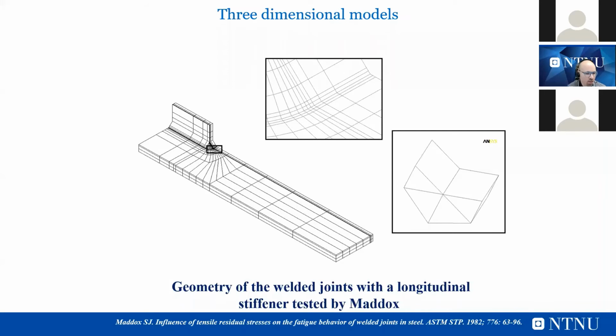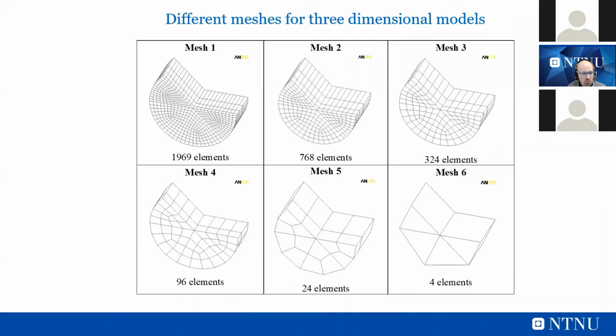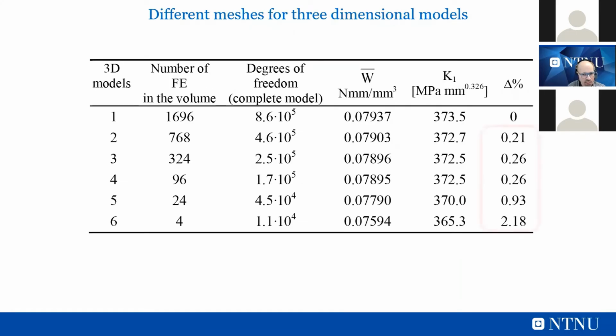Here we use a regular mesh, and in the control volume we put only a few elements. Here we put, for example, 4 elements. But we made a trial with different ranges of elements, and what we obtained is that also with 4 elements inside the control volume you can apply the method very well. So this means that this is a very powerful tool for practical application.